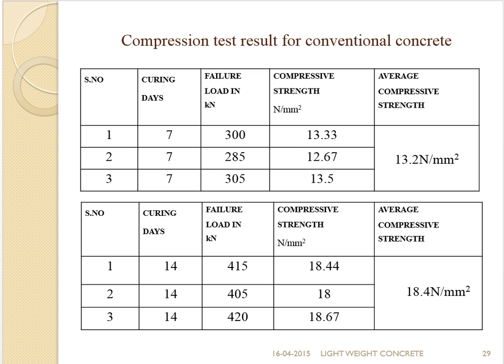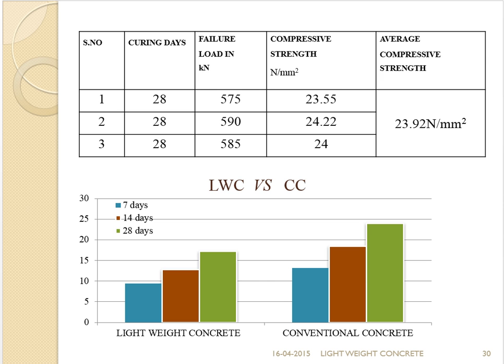When we compare it with the conventional concrete, the compression test result for the conventional is 13.2 for 7 days curing period. For 14 days, it is 18.4 Newton per mm square. For 28 days, it is 23.92 Newton per mm square. The comparison graph for the lightweight concrete and conventional concrete is as shown.